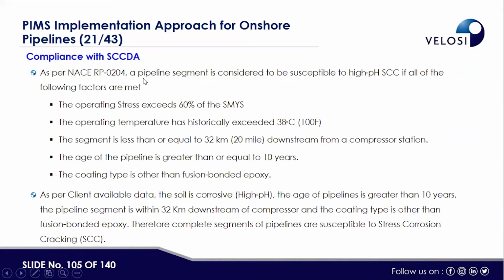And for SCCDA, these are the conditions: the operating stress exceeds 60% of the SMYS, the operating temperature has historically exceeded 38 degrees Celsius, the segment is less than or equal to 32 kilometers, the age of the pipeline is greater than or equal to 10 years, and the coating type is other than fusion bonded epoxy. These are the conditions. And as per the client data, the age, basically this was practically considered not applicable.